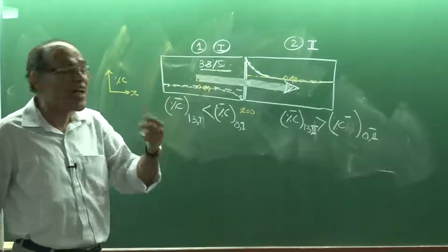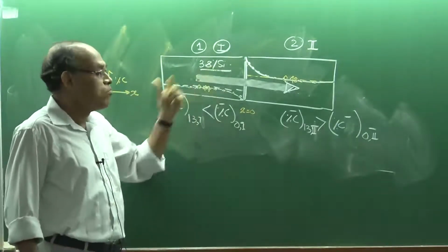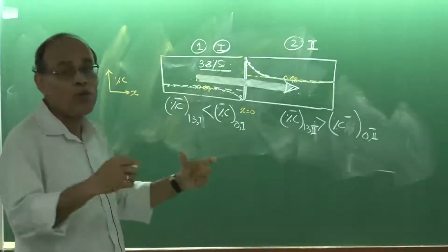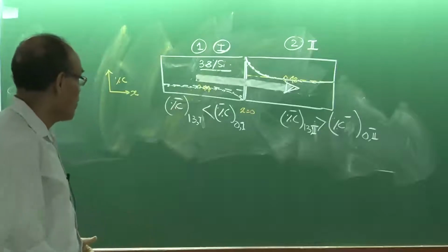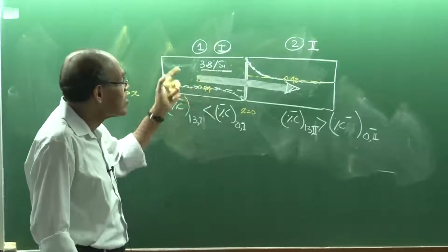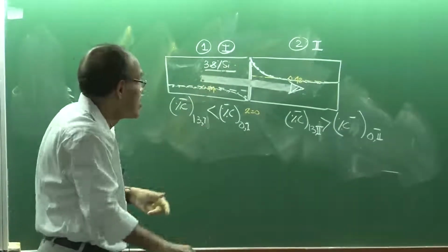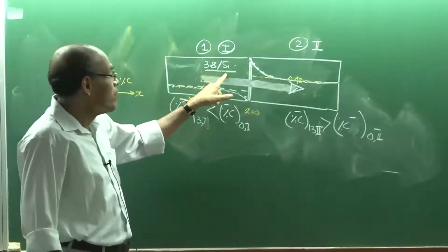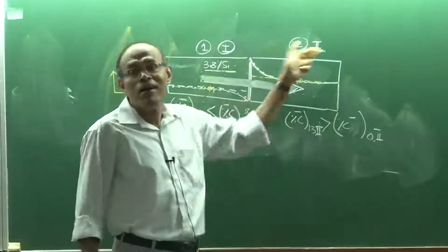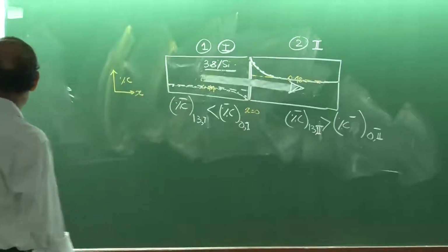I typically explain in the class like this: if you have a person, a Dada kind of a person, in a colony, you will not see another Dada visible there because he will have the apprehension of getting beaten up. So silicon will not try to enter this system. Carbon will not try to enter this system. Carbon will have a greater tendency to leave the system. And the increase of activity of carbon due to the presence of silicon actually causes the flow of mass in the reverse direction in contrast to this particular case.